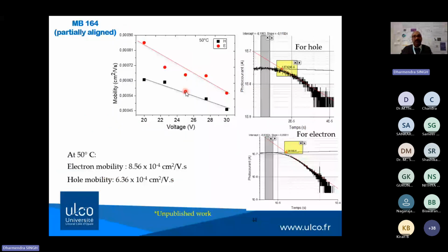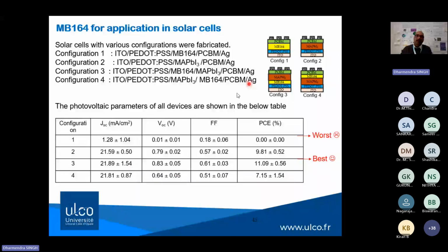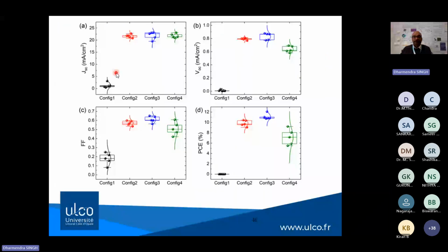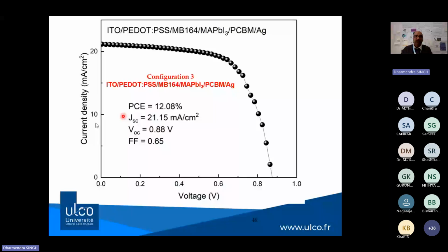And when it is partially aligned, then obviously the charge carrying mobility is lesser than the ordered method. Later on, we also fabricated different devices using these materials. When we use these columnar materials at the interface of the perovskite material in PEDOT:PSS, this showed the best efficiency, around 11%. These are the 4 devices we fabricated, and this was the IV curve of the best device, in which we found a PCE of around 12%.